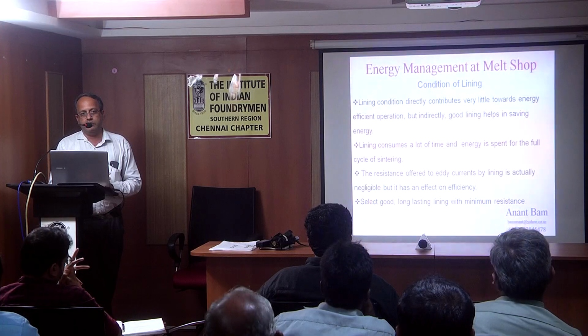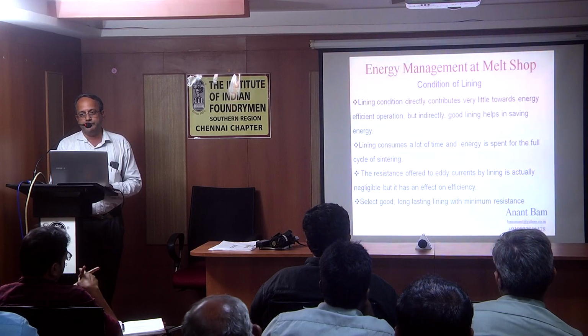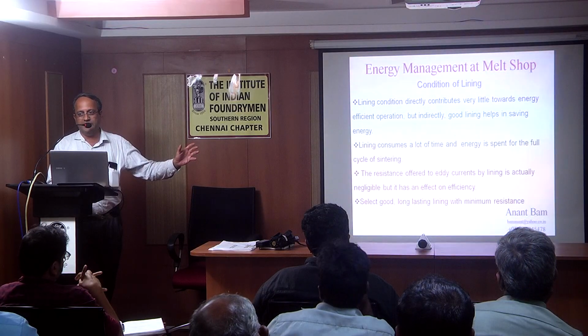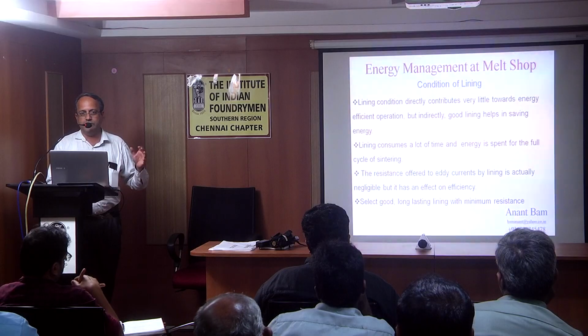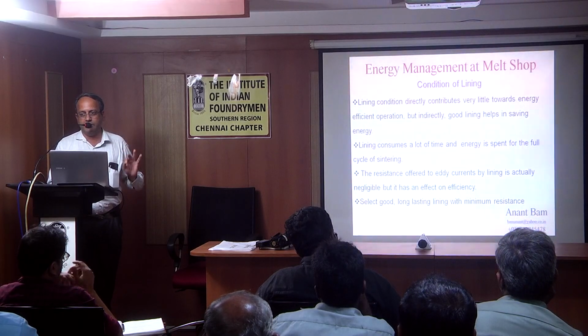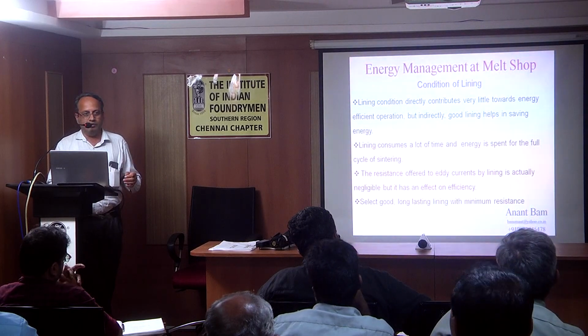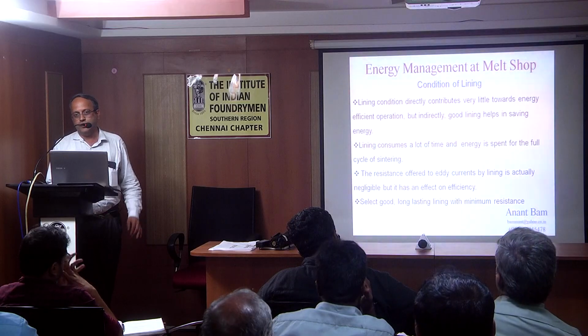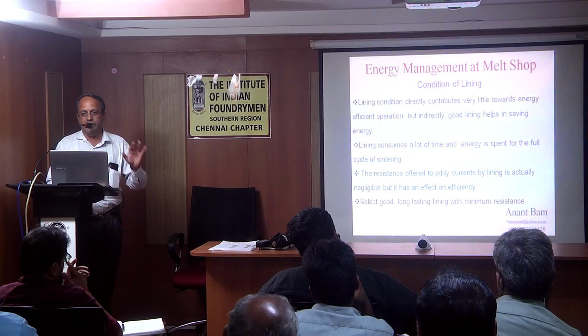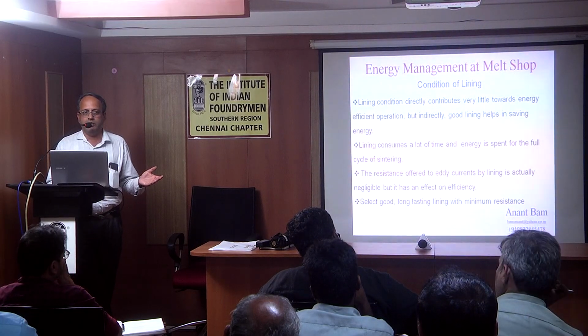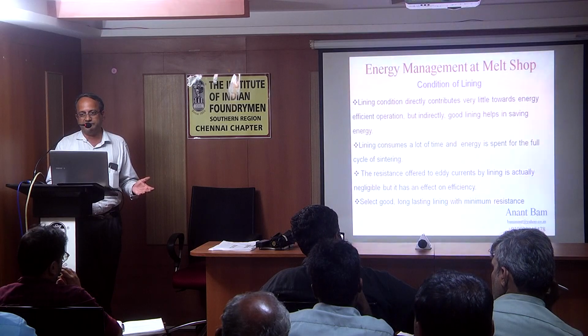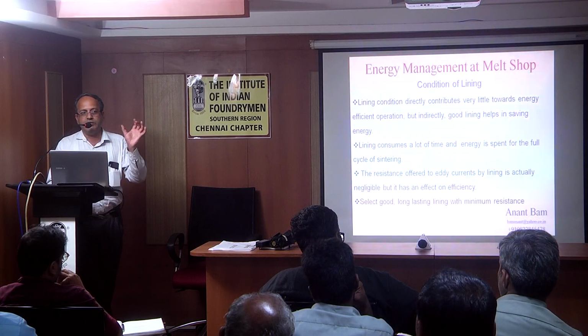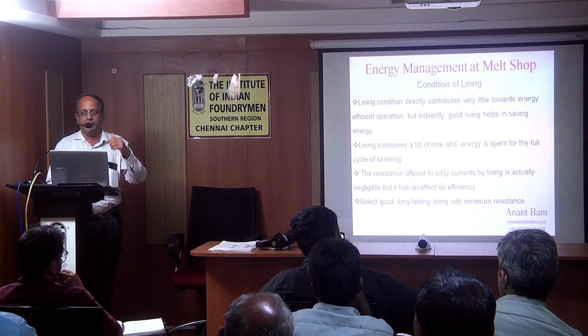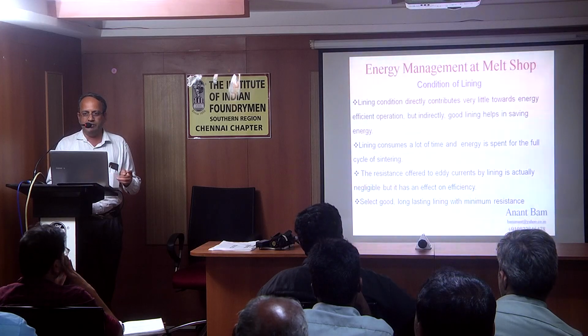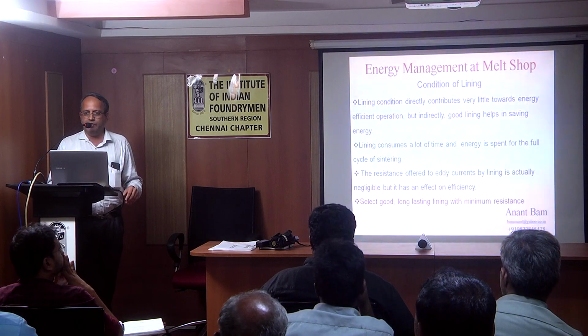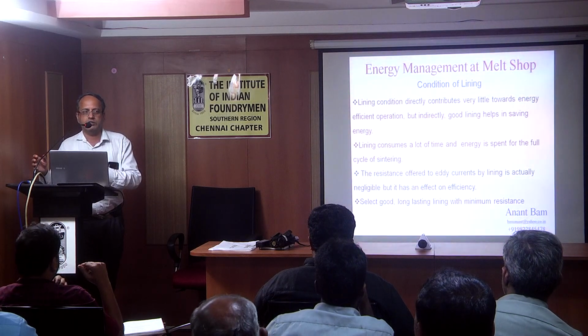Because lining takes up 8 to 10 hours during sintering. So forget about production loss. The energy consumption in lining or sintering is equivalent to nearly 3 heats of energy consumption or more. But it can be done at a minimum of 3 heats. So you are wasting energy for 3 heats and probably production loss of maybe 8 or 10 heats. So that is a tangible figure. Production lost, you cannot cope up again. You have to work hard and hard to come to that figure. So you can quantify that and then allot it to the number of heats sustained by the lining.